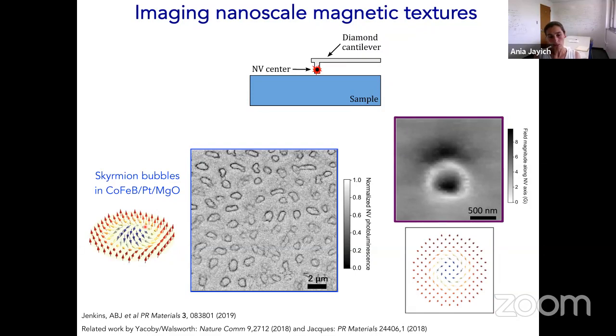But one of the questions is, if one wants to use these types of skyrmion textures, one has to really understand what their local magnetic texture looks like, how the spins are arranged. And what we did is we imaged a material with many of these skyrmions. First of all, one sees that they don't all look nice and round as expected. Again, that's due to local inhomogeneities in the material.